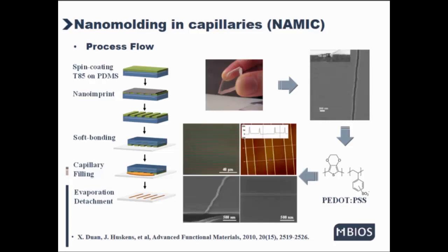From the SEM and AFM results, we can see that the PEDOT:PSS nanowires are successfully fabricated on a large area without obvious defects. And now, the major improvement is the use of a hybrid nanomold with harder, more well-defined features, thus allowing accurate nanoscale surface patterning.